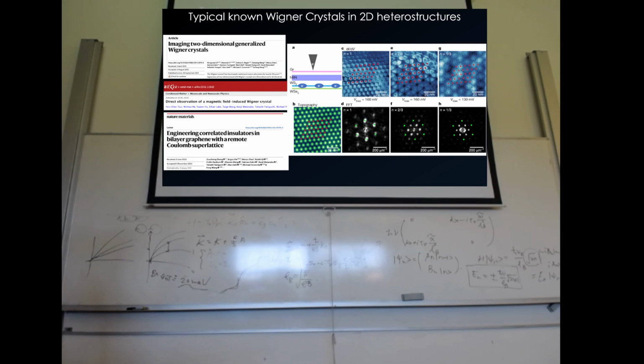For example, we know in a Moiré superlattice of tungsten diselenide and tungsten sulfide, this system creates automatically a Wigner crystal, which is a real Wigner crystal. People found by STM evidence that there are partial fillings when n equals 1, 2/3, and 1/3. There's indeed a possible way to create Wigner crystals, which is defined by Coulomb interaction in such a system.